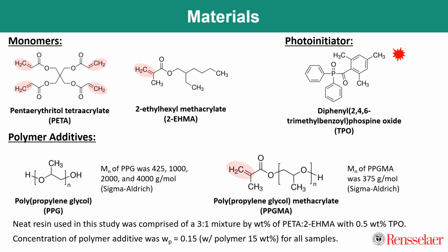So starting with our materials, essentially these are the monomers, photoinitiator, and polymer additives that we used in this study. Our neat resin is comprised of these two monomers on top, PETA and 2-EHMA, and our photoinitiator, TPO. Specifically, we are holding that in a 3-to-1 weight percentage mixture of PETA to 2-EHMA with 0.5% of TPO. Then some samples also included these polymer additives, specifically PPG at these various molecular weights and PPGMA at this 1 molecular weight. And for all those samples, they were held at 15 weight percentage.